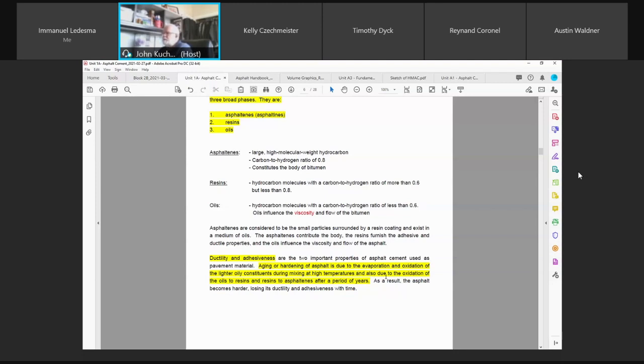You're mixing at high temperatures, and there's also oxidation of the oils to resins and resins to asphaltenes over a period of years. So those of you who have tested asphalt in the industry, say a sample of hot mix asphalt sat in the field office for about three weeks before it even got sent to the lab. That hardened asphalt in a bag or pail went to the lab, they're going to test it, heat it up again, reheating it. Every time you're reheating hot mix asphaltic concrete, you're burning off volatiles, changing the properties of that asphalt cement.